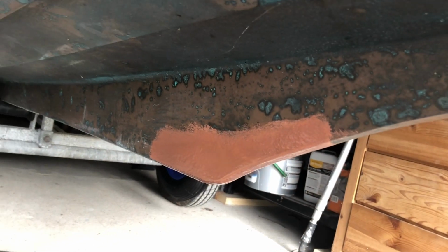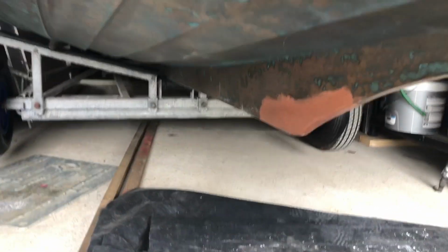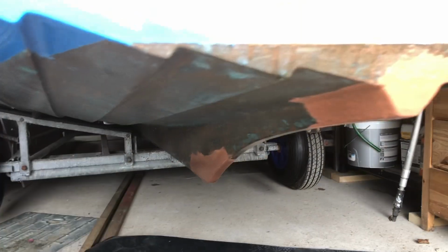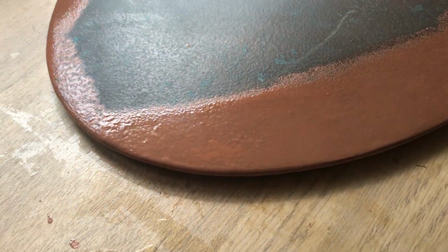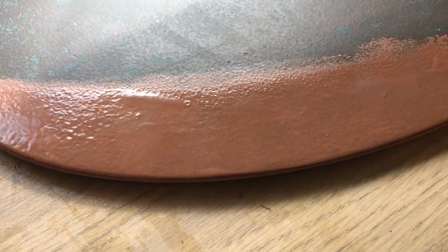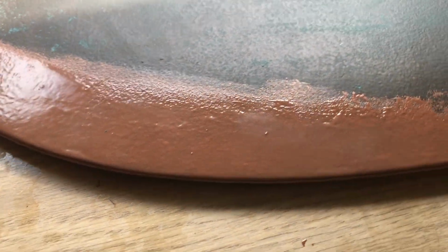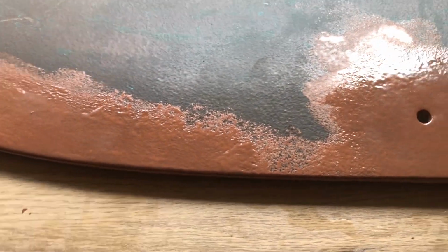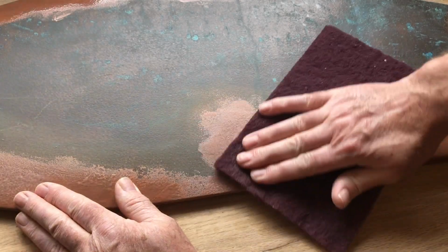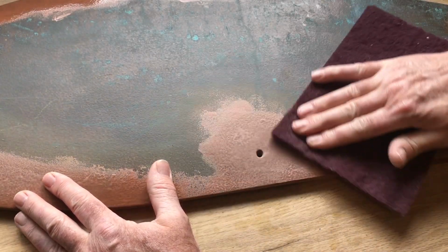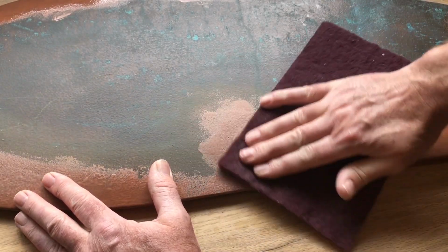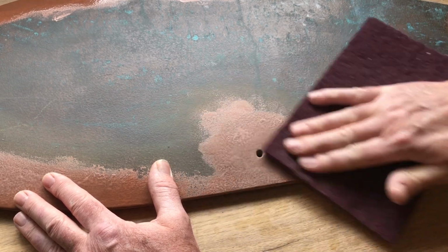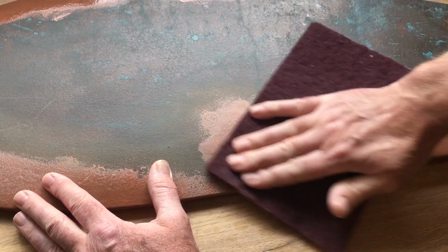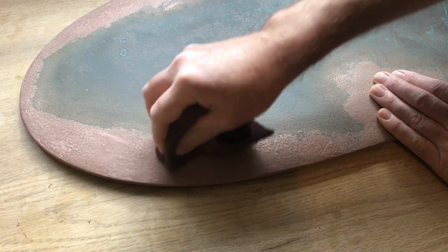While patching the rudder, I also tackled a couple of areas under the hull where the antifoul had been scuffed off. After 5 days of mild summer temperatures in the UK, the Coppercoat was fully cured. My next task was to burnish the surface with a fine Scotch-Brite pad to expose the copper powder and release the full potency of Coppercoat's anti-fouling capability. I burnished beyond the new application to blend the old with the new.